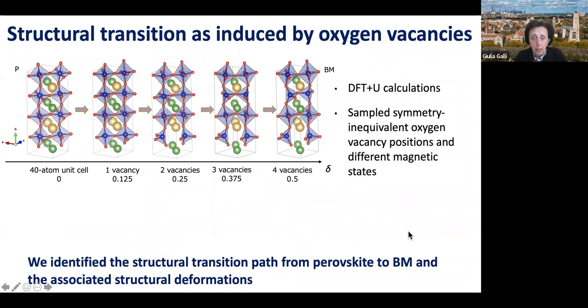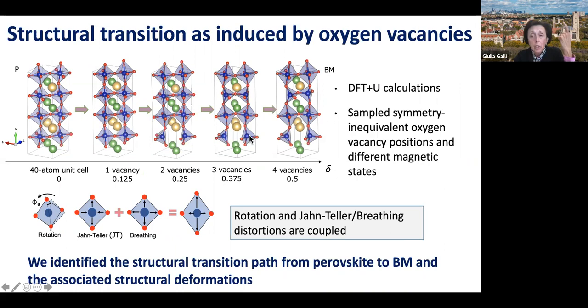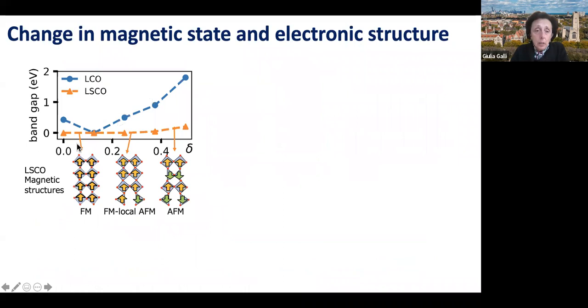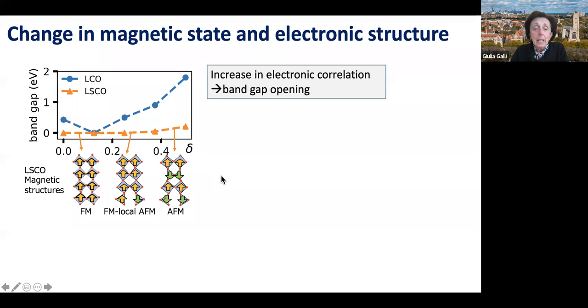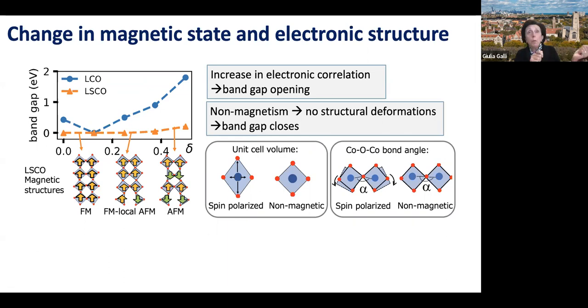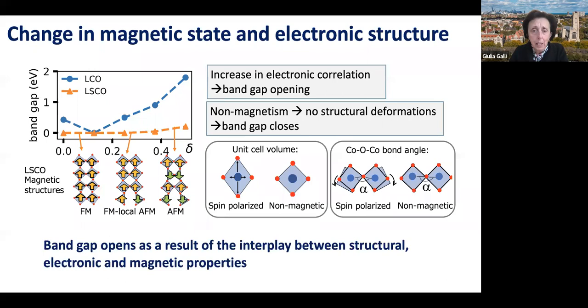First, we identified the structural transition path as a function of oxygen vacancy. And we associated structural deformation with specific electronic property and magnetic property. Again, level of theory not very high, to be checked against experiments and, when we could afford it, against hybrid functional calculations for specific vacancy concentrations. Then we could relate the band gap opening and the metal insulator transition to the change in the magnetic order in the system. And an interesting thing is that if you impose no magnetism, and there is no magnetism in the system, the band gap always closes and you don't ever have an insulator. And so we could understand what is responsible for the insulating behavior. And I realize that I'm going super fast here, but I'm just giving you an idea of what we did.